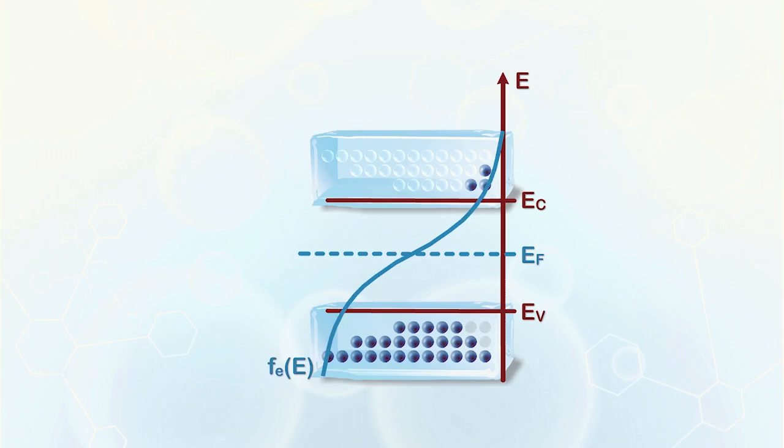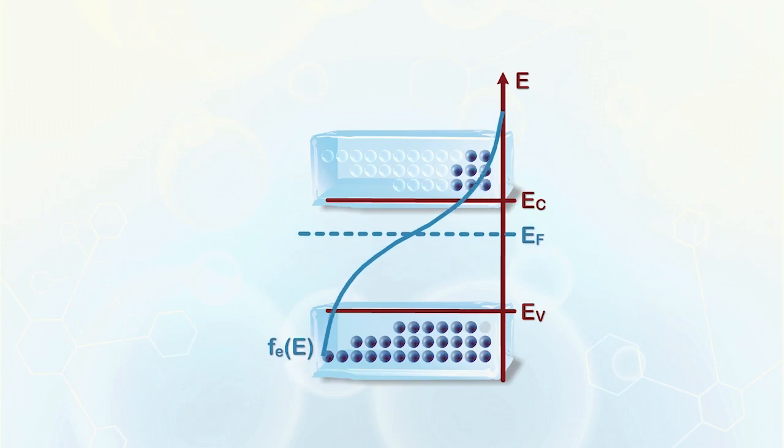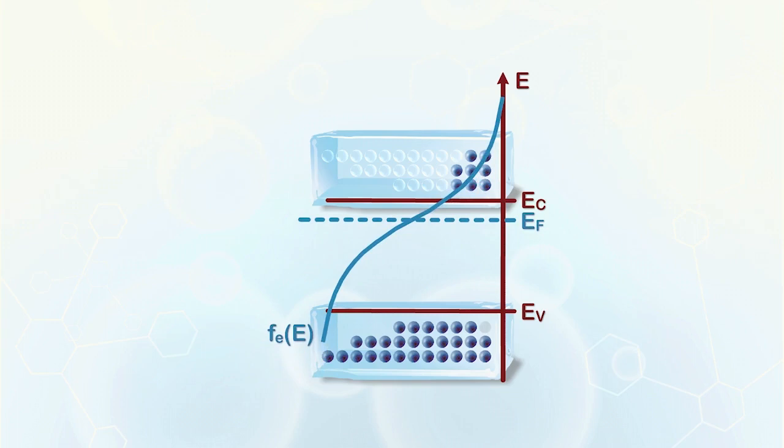As the temperature is the same, the shape of the Fermi-Dirac distribution function remains the same. The change in probability will be reflected by a change in the Fermi level EF. For N-type silicon, it will move up to indicate the higher probability of finding an electron in the conduction band. To give a reference for the location of the new Fermi level after doping, we usually use EI to mark the Fermi level of the intrinsic silicon.